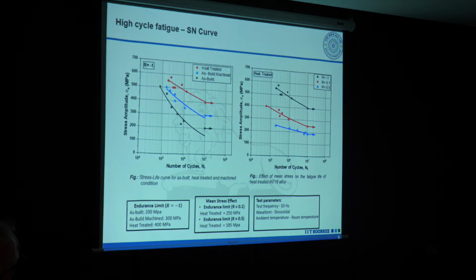Then we performed high cycle fatigue analysis on the same specimens in three conditions: heat treated, as built machined, and as fabricated. We got an endurance limit, the fatigue limit, of 200 in the as built case. The 10⁷ denotes the number of cycles that it ran, so we selected this as the run-out life. The as built machined condition has a limit of 300, whereas in the heat treated case the life has improved, with an endurance limit of 400.